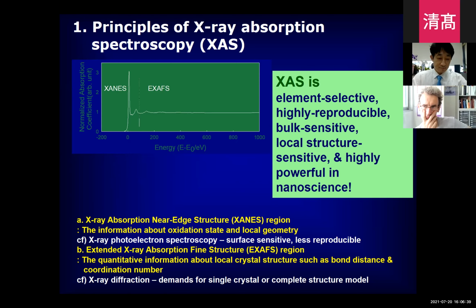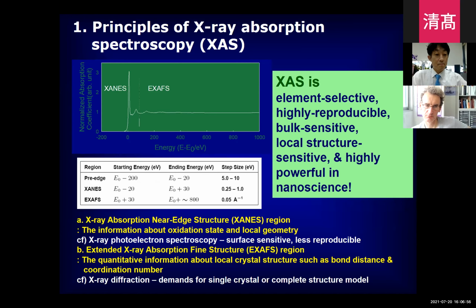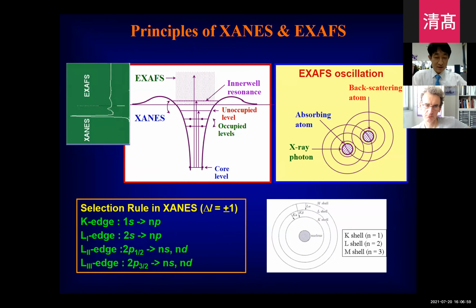Also, we can use XAS to determine the local structure of the materials. We can get quantitative information about bond distances and coordination numbers. From the XANES, we can get information about the transition from the core level to unoccupied levels. From the energy and the intensity of those peaks, we can get valuable information about the oxidation state and bonding nature. And in the EXAFS region, the photoexcited electron has sufficient energy to escape from the absorbing atom, so from the backscattering we can get valuable information about the local structure.